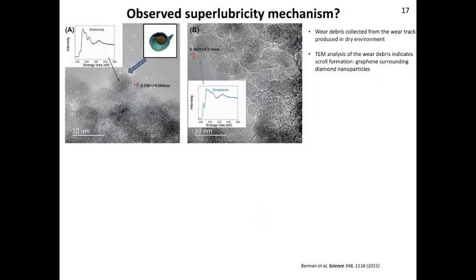To really understand what is happening behind this, we started to analyze the surfaces inside the wear track. This was done by collecting the wear debris from the wear track and looking at it using transmission electron microscopy. What we observed is that all our wear debris has a very interesting structure. They have this diamond lattice surrounded by more graphitic shells of the material. And this was happening everywhere. To demonstrate, by going in and out of focus, we tried to understand how exactly they look. Inside the focus, if we focus well enough, we see this diamond lattice. If we stay a little more out of focus, we see only these graphitic shells.